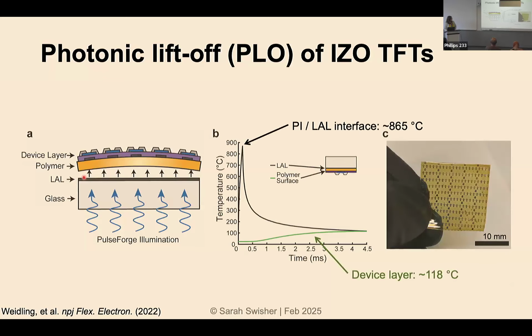So then when we shine the light on the back of the device, the temperature profile looks like this. So this is the temperature as a function of time. And this black peak right here is showing the temperature at the interface between the light absorber layer and the polyimide. So this is the interface where we're getting that ablation. And the green line down here is the surface of the polymer where the device lives. So you can see that our device layer is only getting up to about 118 degrees. So again, this tool gives us the ability to have this big thermal gradient where we can heat the layer that we want to without heating the layer that we don't want to heat.